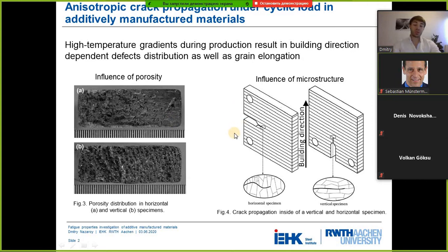It should also be noted that the microstructure of additive manufactured steels consists of elongated, columnar grains, because the grains grow in the direction of heat transfer. And with regard to the applied notches, the crack could propagate along the columnar grains or transversally, taking shorter or longer routes, and this has an influence on the rate of crack propagation.